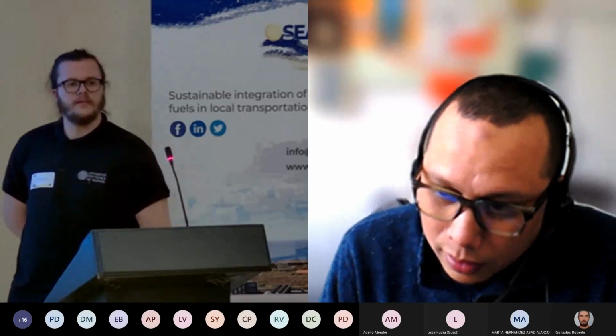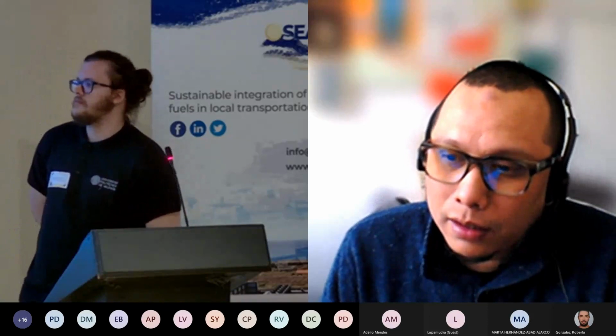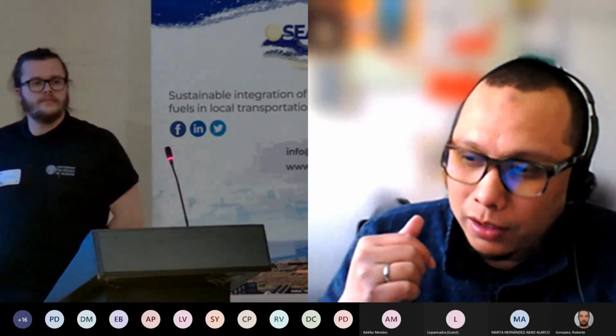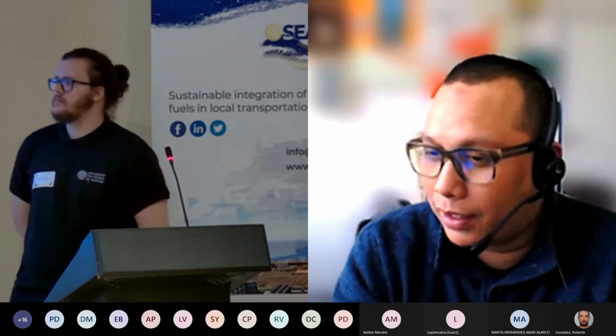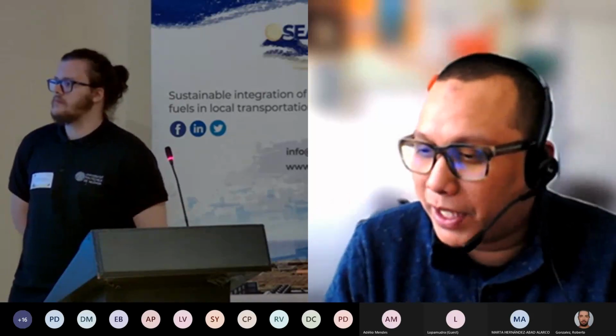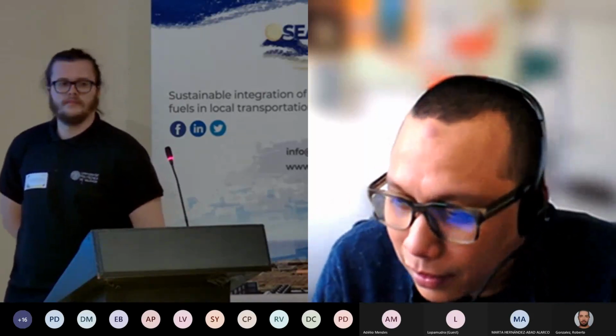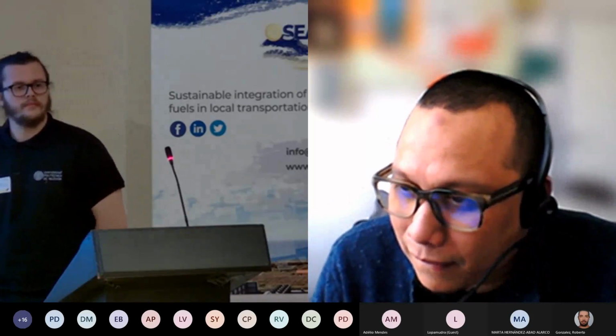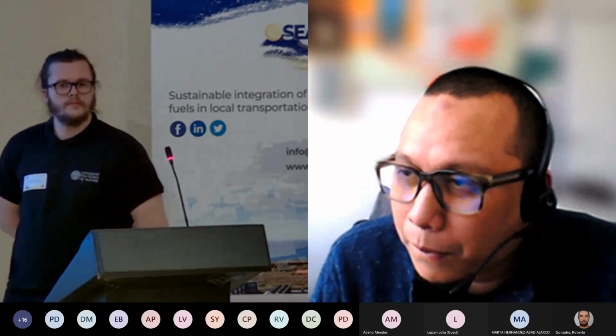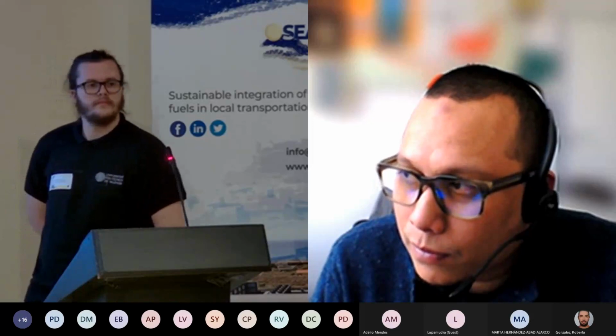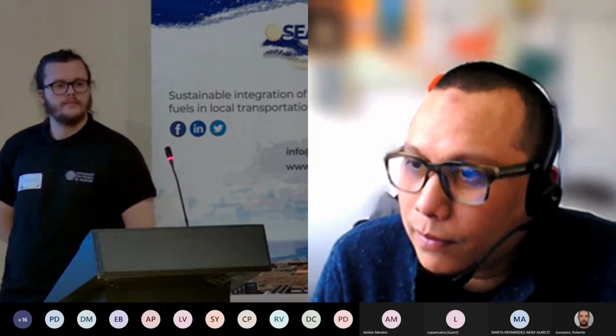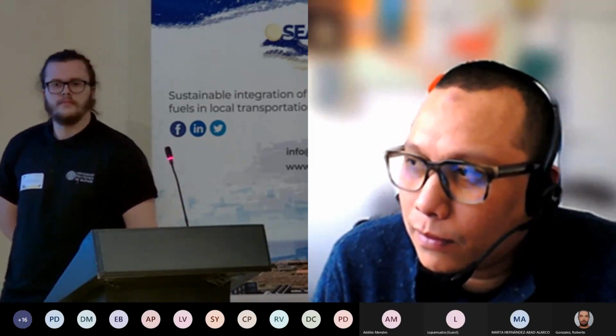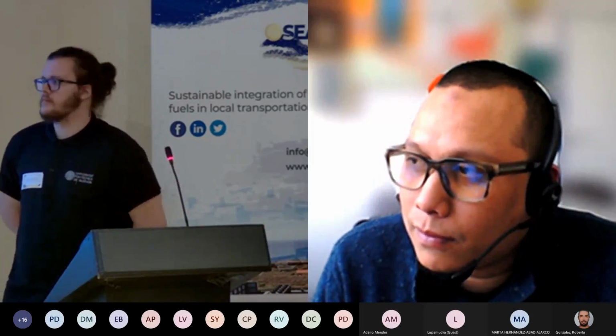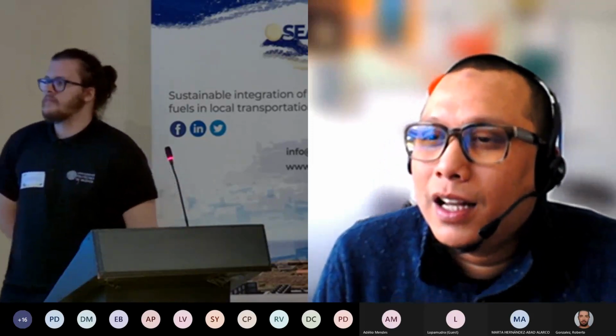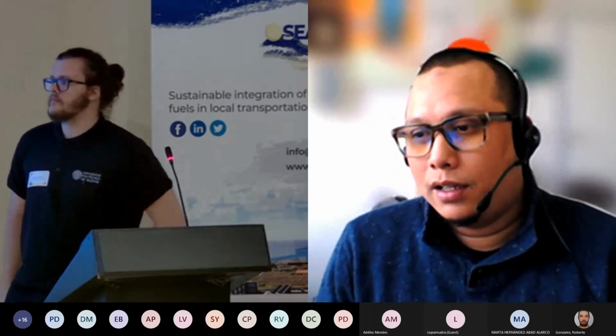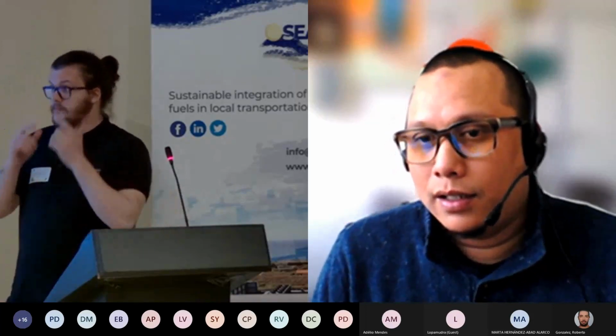Photoelectrode efficiency decreases when you increase the photoelectrode area. I'm sorry, the question was interrupted at the beginning, and I couldn't catch it. So you showed nicely that the photoelectrode efficiency decreased as you increased the photoelectrode area. What happens if you go smaller than 0.3 centimeters squared? Can we actually see higher efficiencies, or are we already at the highest we can get intrinsically from a bismuth vanadate material?